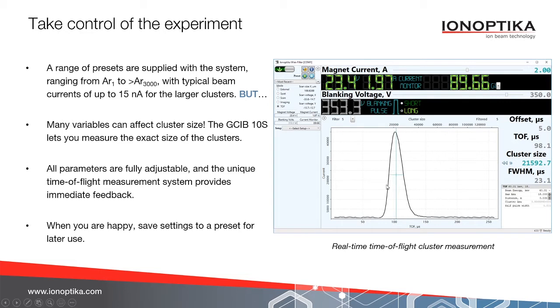So here we have a real-time graph of the cluster measurement. Here it's telling us what the cluster size is, what the time of flight is, because this measurement is achieved via a time of flight measurement from the source to the sample. We can tell it what the energy is and what the gas is. Now, this particular screenshot was obtained on another gas cluster ion beam that we provide, which is a high energy water beam. So excuse these numbers, they will not be the same for the GCIB 10S, but the operating system is exactly the same.